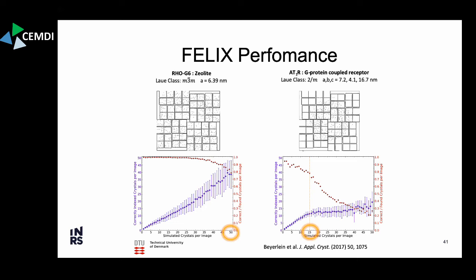And so you can see in the blue, the number of correctly indexed crystals as a function of crystals per image. And there's also how many correct versus the found numbers of crystals. So in other words, it can still find extra, but then if you have, say, 10 crystals contributing to that diffraction pattern, the algorithm might find 15. And so then how many extra crystals is it finding? So that's the other metric that I have over here.